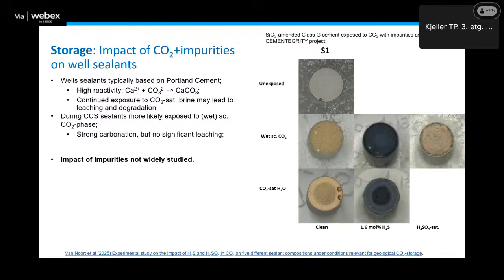But then what's the impact of impurities? This has not been studied so widely, but here we see the same sealant again, exposed to CO2 with 1.6 mol% H2S, either underwater or above water, and exposed to CO2 in the presence of concentrated sulfuric acid. So in the same autoclave, we had the samples, a CO2 phase, and concentrated sulfuric acid to create a realistic H2SO4 SOx concentration with a big quantity, so that the batch process could keep going. And we see some very clear differences in how these samples look, especially with the H2S, of course, where oxidation states are going to be very different.